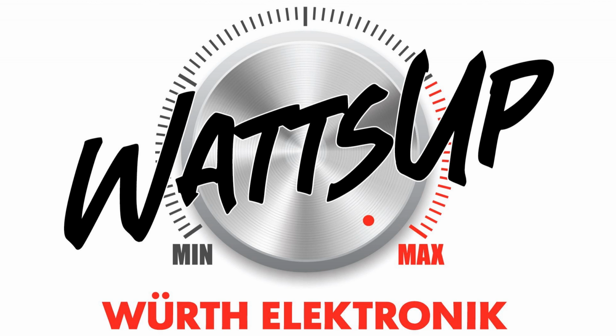We specify our chip bead ferrites with zero bias. This is something important to keep in mind. So therefore, we only show you the impedance that you will get with no current flowing through the part. So for example, this slide shows 330 ohms of impedance at 0 amps. So if you were to add current flowing through the part, you will be saturating the core. If you saturate the core, the impedance drops and the frequency shifts. We do have LTspice models, but only for our high current chip bead ferrites, so you can run your simulations.